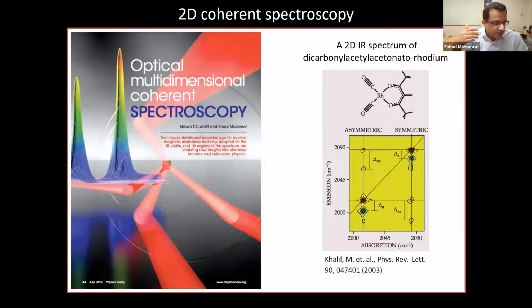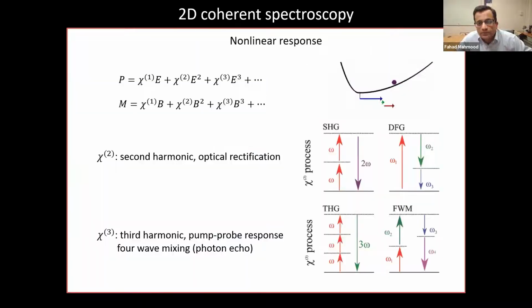If you want to attack a strongly correlated material, I want to implement this technique in what's known as the terahertz range of frequencies, because that terahertz range is very suitable for correlated materials, because that's the energy scale over which a lot of these correlations occur. Okay. So just to describe exactly what we're measuring when we do these type of measurements, we'll be measuring a higher order susceptibility rather than just the linear susceptibility of our system. So for example, we could either measure the second harmonic generation or a third harmonic generation, but there are various ways of probing this chi-3, or the third order susceptibility, using these type of multidimensional techniques.